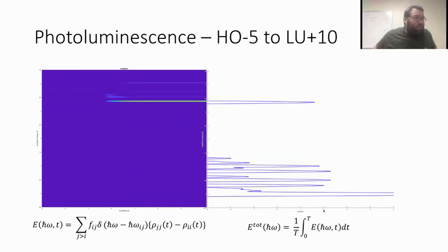Right. Yes. So this one, HOMO -5 to LUMO +10, is about 4.9 eV excitation. And the reason we're not seeing a peak at 4.9 is because it relaxes to the band gap or near the band gap, and that's where the radiative relaxation occurs. All the relaxation before that is non-radiative. If you look at the peak, it's a little hard to see because it's quite dull, but you do see some small lines above the main line at 3.3. They're just not very intense, as you can see in the intensity graph.